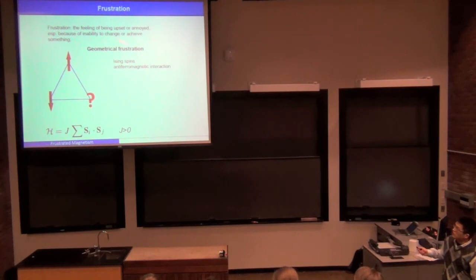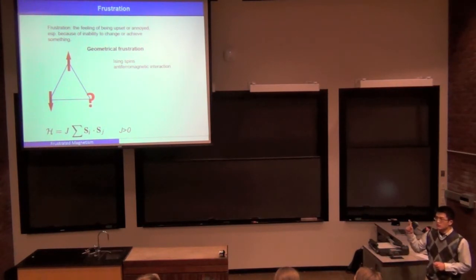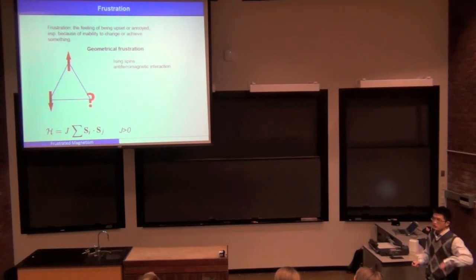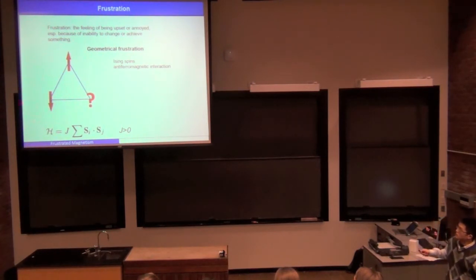Let's take a look at a particular way called geometrical frustration, where frustration is brought in by a special lattice geometry. Here, suppose we have a triangle lattice, and we have the nearest neighbor interaction between the spins, and the spin interactions are of the antiferromagnetic type. So if one spin points up, then every neighboring spin prefers to point down. If we put two spins here, then this spin will point up and this spin will point down. Then what about the spin here?